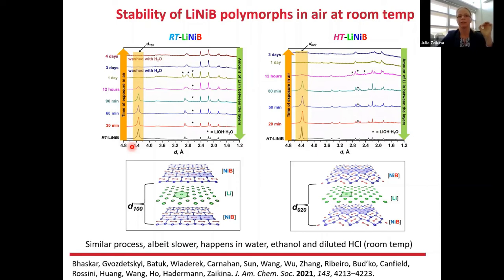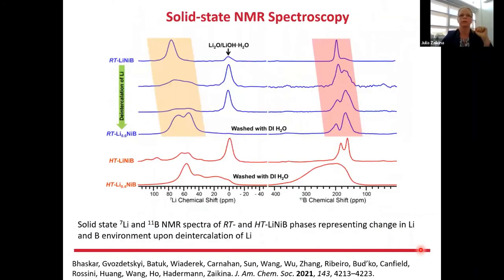polymorph. And interestingly, a similar change in the powder pattern is observed when we expose our material at room temperature to water, ethanol, and even diluted HCl. So we were curious to see whether all of the lithium can be removed this way. So we used solid state NMR spectroscopy for both lithium and boron, and with increasing the exposure time, we do see a change in the peak intensity corresponding to the lithium in the structure of our layered lithium nickel boride.